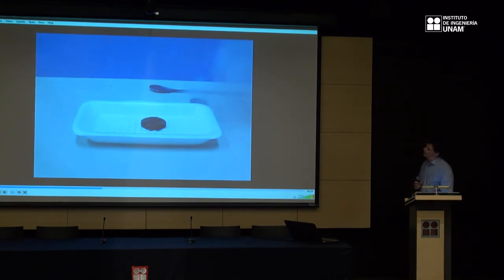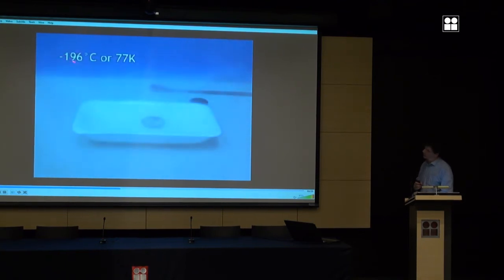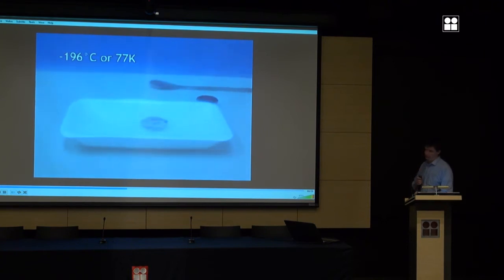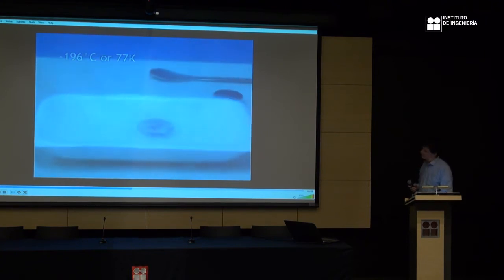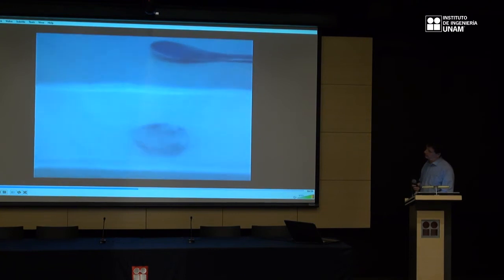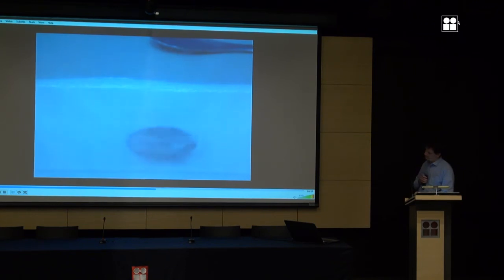The smoking liquid that is being poured out on the superconductor is liquid nitrogen. Its temperature is 196 degrees below Celsius, or 77 degrees Kelvin. The liquid near the superconductor undergoes intense boiling due to the heat that the liquid nitrogen absorbs from the superconductor. So here you have bubbles, it's boiling. Liquid nitrogen becomes nitrogen gas, and the temperature of the superconductor drops gradually.